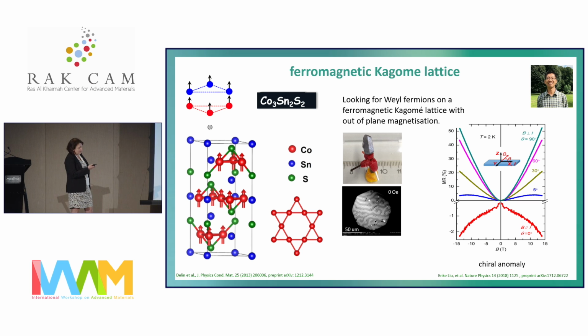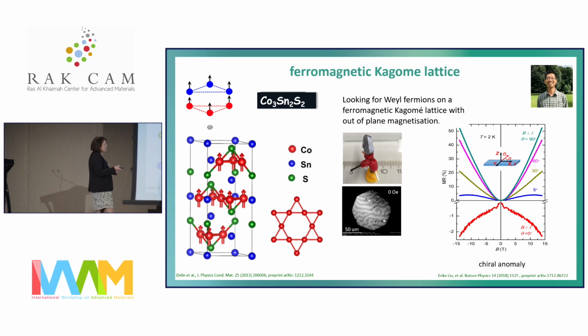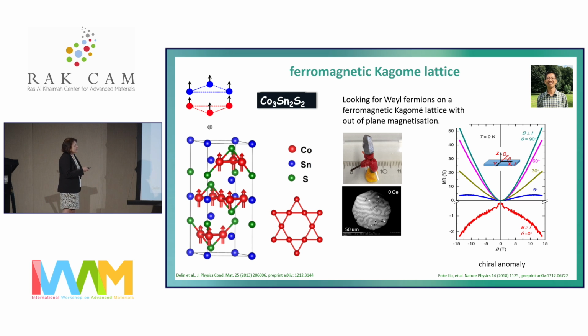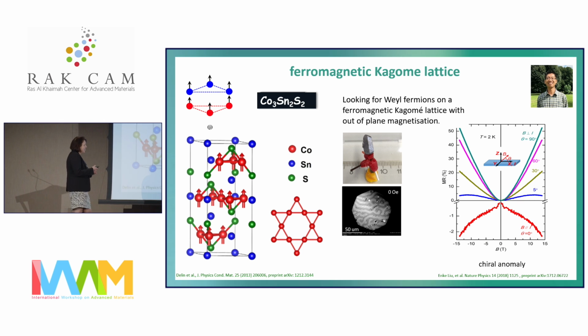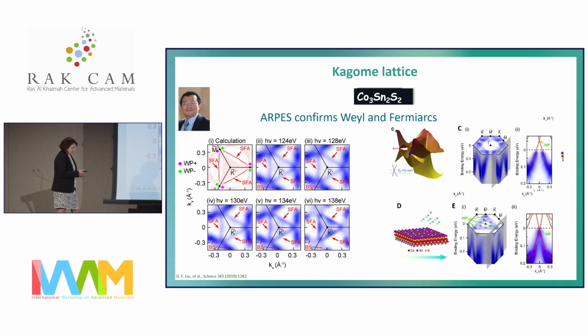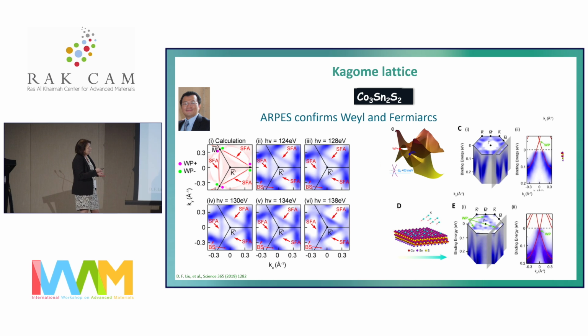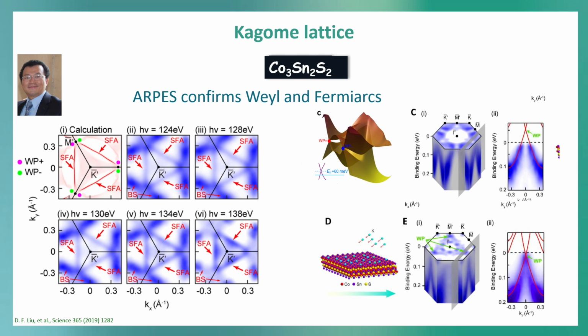So we made this compound as a single crystal, and we showed the chiral anomaly in this paper. This was simply because the editor wanted to see the chiral anomaly, because everybody is excited about this high energy physics property, but it has no impact at the end of the day. But it shows that depending on how we measure our magnetic field relative to the current, we see a positive or negative magnetoresistance effect, which shows evidence that we have this physics. But we also saw in photoemission experiments that we have this linear dispersion here, a little bit above the Fermi energy in the virgin compound as predicted by the calculation, but we had to put some potassium on it and we saw the crossing.